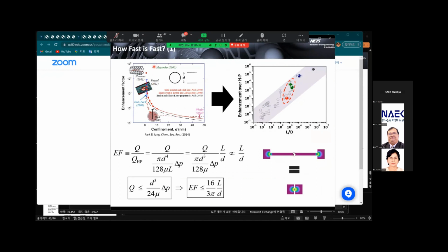Fortunately, there are 2 data points sharing similar CNT diameters. One is my old data from 6.5 nanometer wide short double-walled carbon nanotubes, whereas the other is from long multi-walled carbon nanotubes. My student and I speculated that the length plays a role in this diagram and replotted the flow enhancement factor with respect to the length over diameter. Then it appears that most of the published data from both experiment and the simulations collapse on a monotonic line in this new diagram, and the exponent in the log-log plot was close to unity.